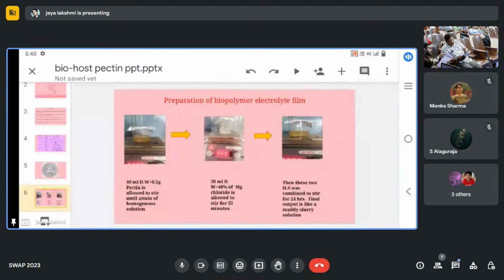And this is my preparation of the biopolymer electrolyte film. For the biopolymer, I take the pectin, and for the ionic provider, I take the magnesium chloride. First, I dissolve the pectin in 40 ml distilled water and allow it to stir on the stirrer for a few hours until it attains a homogeneous solution.